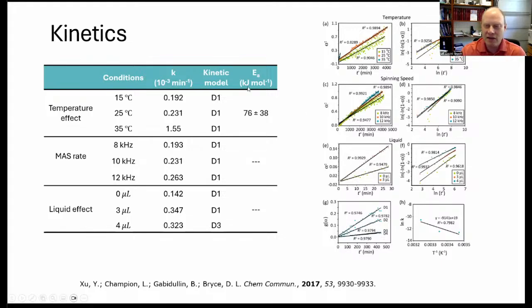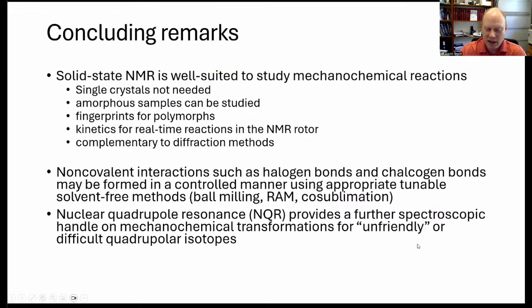And we were able to get out an activation energy for the formation of this halogen bond, albeit with a large error. But nevertheless, I think probably the first direct measurement in the solid state in real time between these two powders forming the halogen bond as you're doing the NMR experiment. So I think that's half an hour, 35 minutes or so.